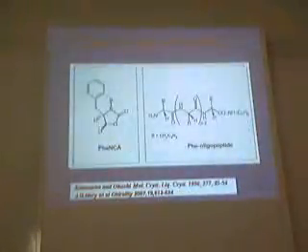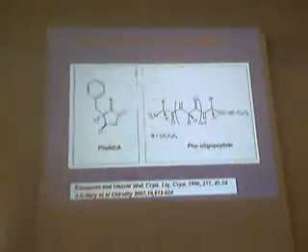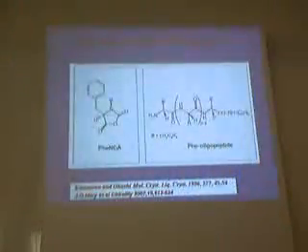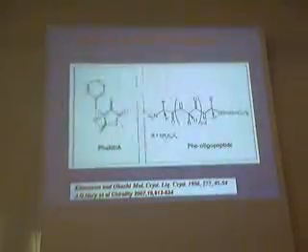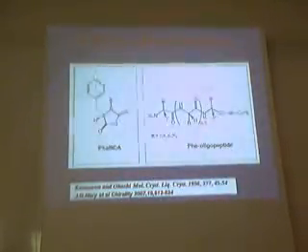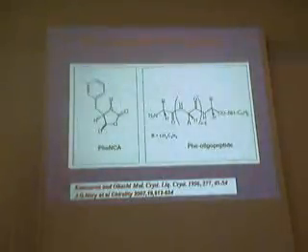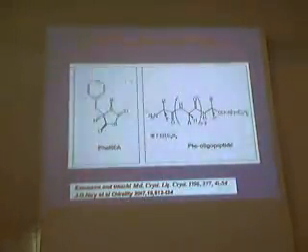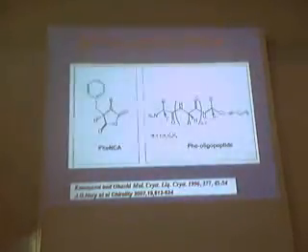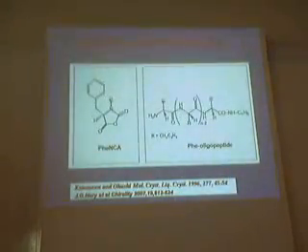So the next problem was, let us go to three-dimensional crystals. It was not a simple conversion to three-dimensional crystals because I did my PhD in polymerization in crystals. I learned this field quite well at the time. And I knew one thing, that if you polymerize a monomer in a crystal where the density of the polymer is higher than that of the crystal, the control of the crystal in this reaction can be in the stage of the dimer and the trimer.